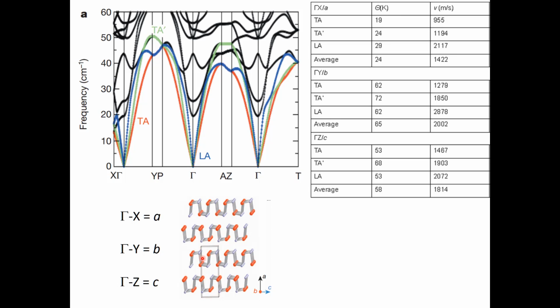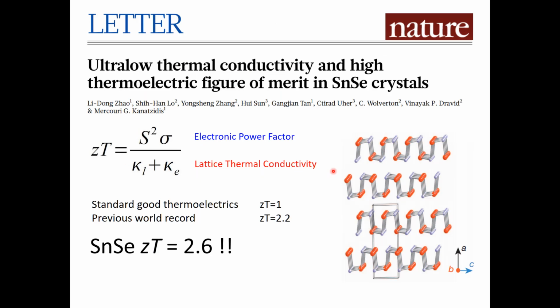But in this direction, you have very soft phonons, and that gives us this result where you have very low lattice thermal conductivity, and so you have very high ZT. Pretty cool, right? It's pretty cool. So this is how you can use all this stuff to engineer new energy materials. Okay, so thermodynamics is important. That really is the end of the lecture.